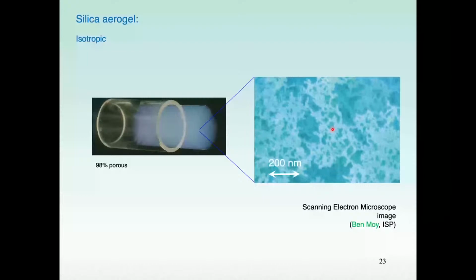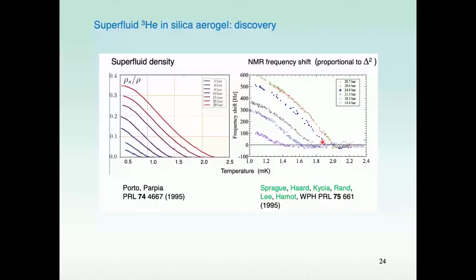Nonetheless, the long mean free path of superfluid helium-3, which is embedded in this structure, averages this out. And you get very sharp thermodynamic transitions for helium-3 in this environment. And here is the discovery of superfluid helium-3 in silica aerogel by the Cornell group. This is Jeevak Parpia's group, and Northwestern as well. In the first case, it's the superfluid density that's measured by a torsional oscillator. And in the second case, it's NMR frequency shifts. And just as they were observed in the pure helium-3 case long before, there is a classic signature of the onset of superfluidity. But I should add, rather suppressed from that of what was expected in the pure helium-3 case, both for the superfluid density as well as these frequency shifts. And the latter, the frequency shifts of the NMR spectrum, scale as the gap squared.